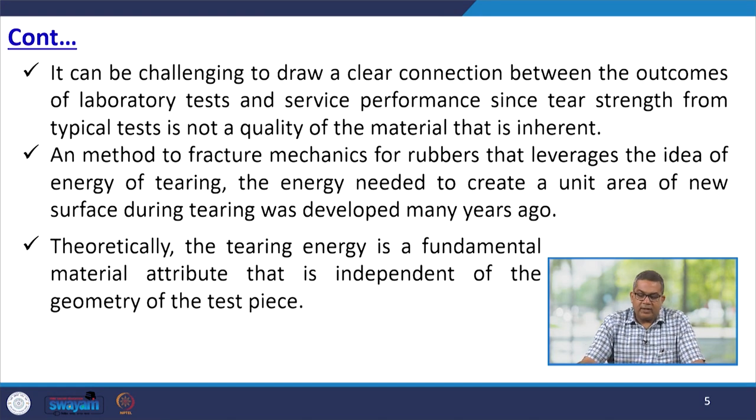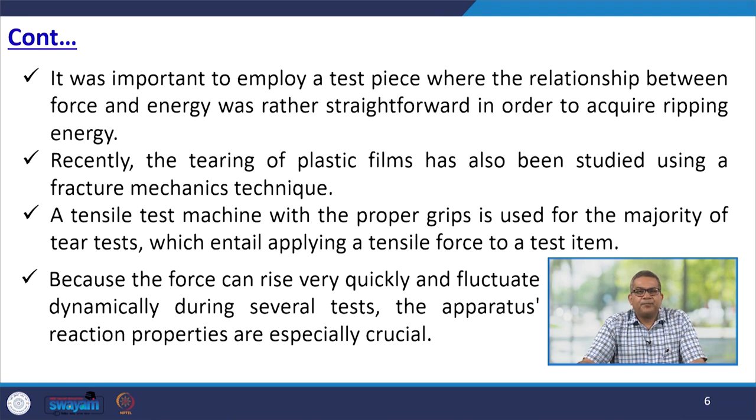Now, it can be challenging to draw a clear connection between the outcome of laboratory tests and service performance, since tear strength from typical tests is not an inherent quality of the material. Now, a fracture mechanics approach for rubbers leverages the idea of the energy of tearing, the energy needed to create a unit area of new surface during tearing, which was developed many years ago. Theoretically, the tearing energy is a fundamental material attribute that is independent of the geometry of the test piece. So, it was important to employ a test piece where the relationship between the force and energy was rather straightforward in order to acquire the tearing energy.